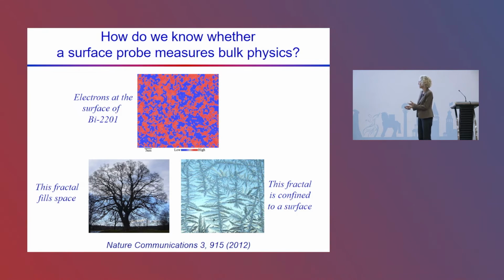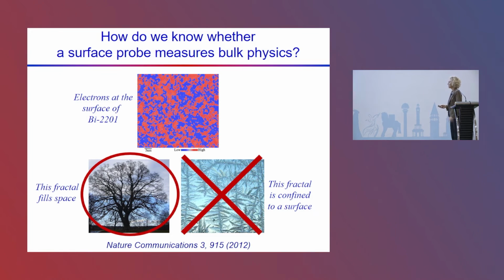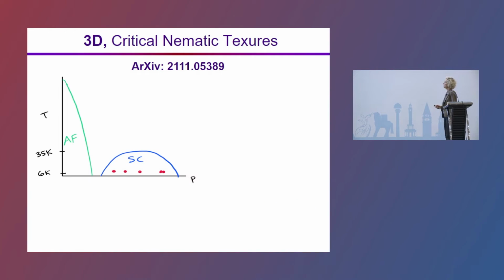You wouldn't be confused between the case where it's something growing on the surface and something that's in the bulk. Likewise here, with a critical exponent analysis, we include the fractal numbers here as well as some other critical exponents. We've ruled out this case. It is not the case that this pattern formation is some pattern that's growing only on the surface like frost growing on a window. This is much more like the tree that's happening deep inside the material, and then we see the intersection of it with the surface. So, yeah, we've ruled out the 2D case. It's a 3D phenomenon.